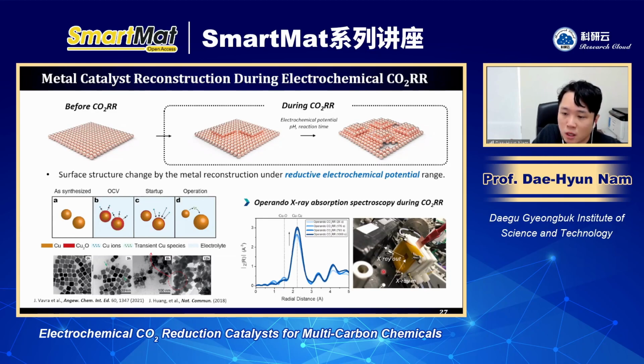So for example, if we measure this XAS, we can see how the oxidation states and the coordination number of copper change during the cell operation. As you can see, this peak shows the bonding with the copper-oxygen, and this peak shows the bonding with the copper. As the reaction starts, we can see the decrease of the copper-oxygen peak here.